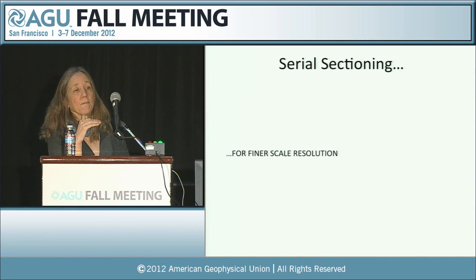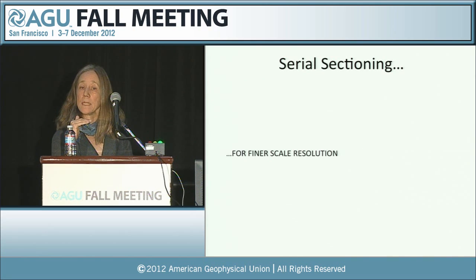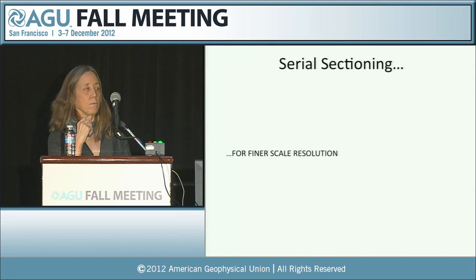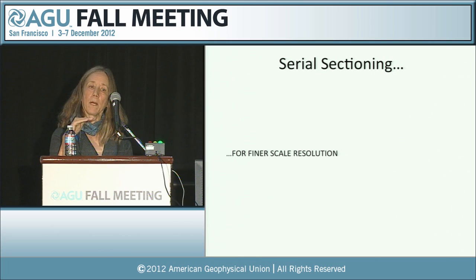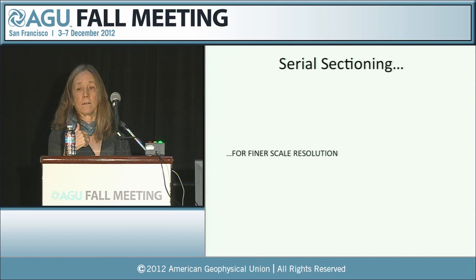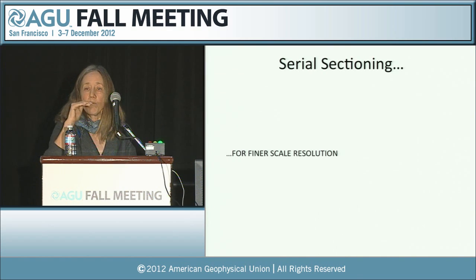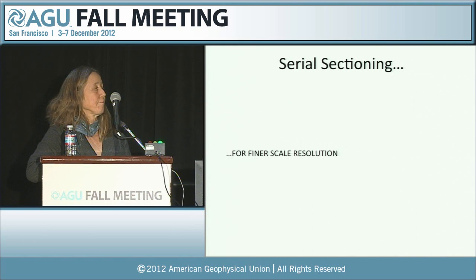The approach that we've taken is a third approach, which is to use serial sectioning, where we've oriented the zircons so that their rims are at the top of the ion probe mount, and then we bombard them with the ion beam that way. In that way, we're able to get a rim analysis. We had tried this once before, and I'll give you some new data showing that. And then we would polish them down to known depths and do another analysis, a sequence of analyses, so that rather than going across the stratigraphy within the zircon, we can look at the stratigraphy as we're going downwards through the crystal.